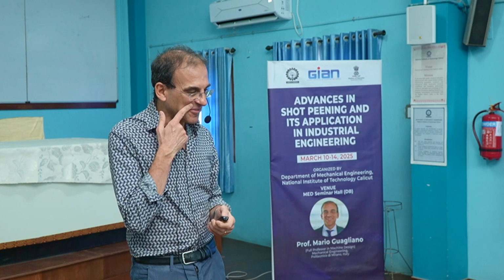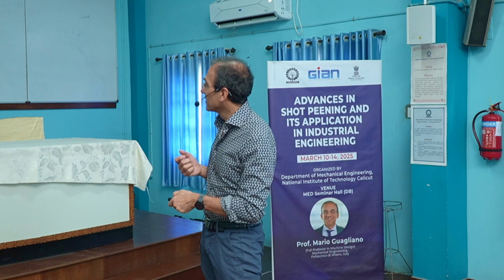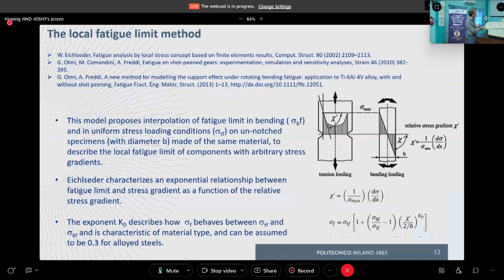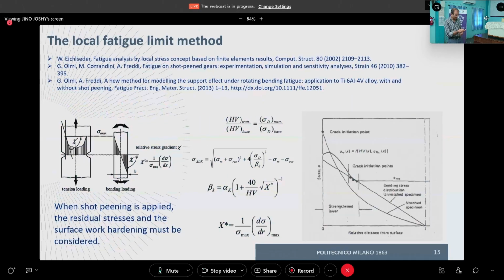Anyway, there is this formula that is applied here, but we could apply also this other formula. That is another interpretation, let's say, formulation of the local fatigue limit. And others can be found in the literature, but as I said, the concept is always the same. By means of the local fatigue limit, we recognize that after surface treatment, the properties of the material at the surface are different with respect to the core, and are increased. And we find some formula to define this increment, and then we can draw the trend of the fatigue limit by using the formula that we have adopted.